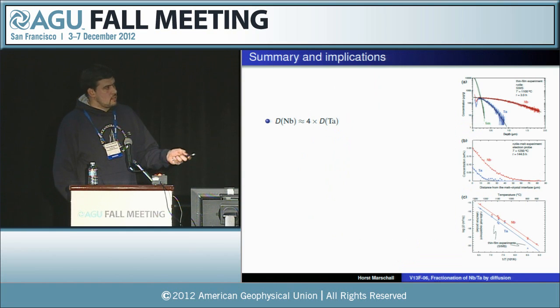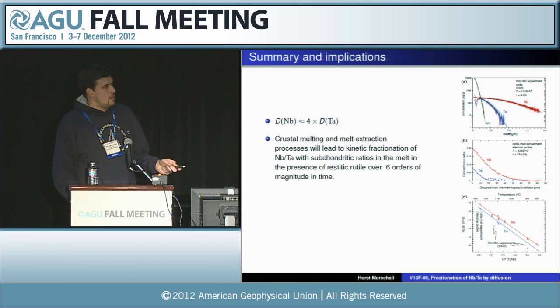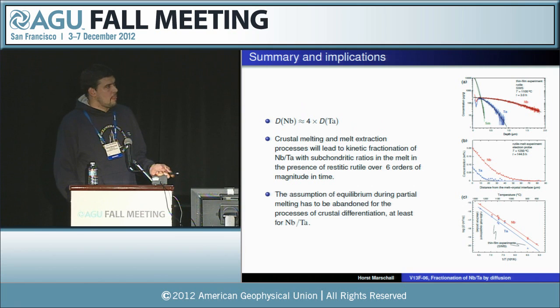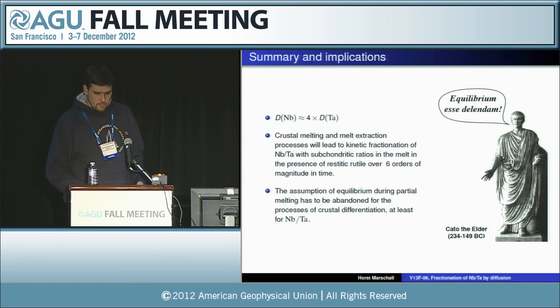So just to summarize this, niobium is much, much faster than tantalum. You can easily see that here. Crustal melt extraction processes will lead to kinetic fractionation of niobium-tantalum, and this will happen over 6 orders of magnitude in time. And so the assumption of equilibrium during partial melting has to be abandoned here, at least for the niobium-tantalum element pair. And I want to point out that Senator Cato is with me on this conclusion. Thank you.